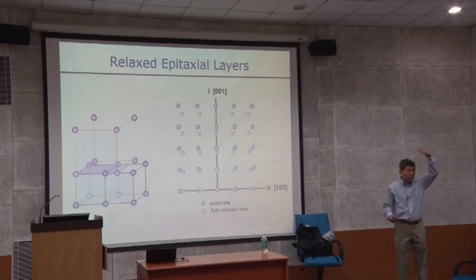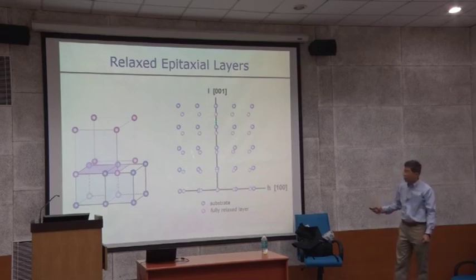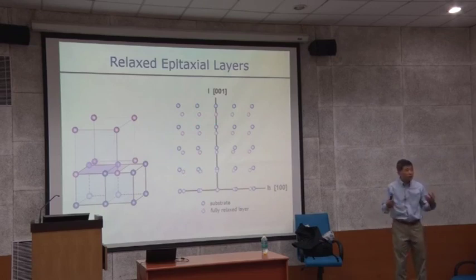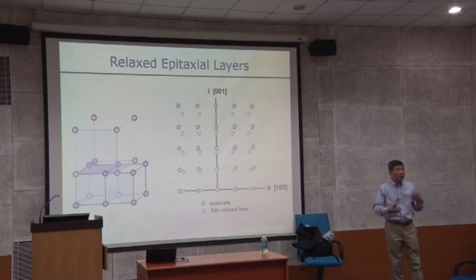So we plot this reciprocal space lattice, cut a slice of reciprocal space, H direction and L direction. From those, whether these two are lined up along this direction or off center tells you coherent or incoherent, without going through all the calculations. So there's a simple way to do that.